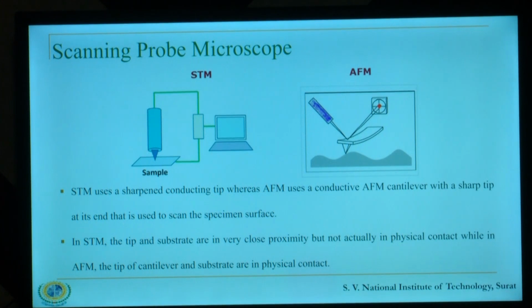So there are two ways in which we do this. In case of STM, a sharpened conducting tip is used, and in case of AFM, a cantilever is used. Because of that cantilever, it is able to sense the Z feature, and that helps to give you the X, Y and Z positions. There is a physical contact that happens in case of this cantilever AFM, whereas in the other case there is a force of attraction in between, and there is no physical contact happening.